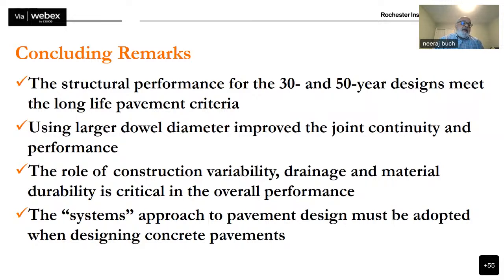Regarding the strength, you don't need high strength in paving concrete. 20 to 25 megapascals is more than enough to sustain, because remember, this is a slab. We are relying on the slab action. We are not relying on the individual strength of the concrete to carry the load. We are designing a system. We are designing slabs. We've got dowels. We've got joints. We've got multiple connected slabs that are going to transfer the deflection, as well as the stresses. But we don't need 40, 50 megapascal concrete strength in order to carry the load.